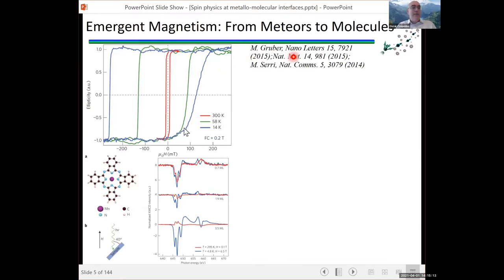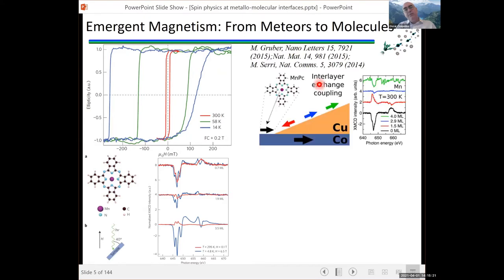And later they did the same thing, and they published in Nano Letters, but what they did is they had the cobalt substrate and the manganese phthalocyanine separated by a few atomic layers of copper. And what they noticed is that when the cobalt and the manganese phthalocyanine are directly in contact, they did some XMCD measurements, and they have a ferromagnetic coupling between the manganese center of the molecule and the cobalt substrate.